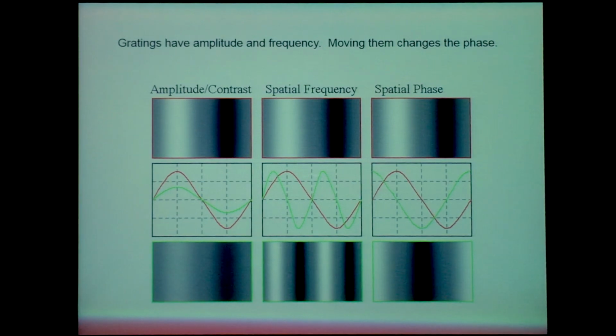And we can sort of express that in the form of a cosine curve, where the peaks represent where the atom is, and the trough represents where it's absolutely not. In the real case, we ignore this trough here. And I'll get into how we can ignore that in a minute. Now, this has a certain intensity, which is due to the atom type. So if it's a selenium atom, this is quite intense. If it's a carbon atom, it's less intense. So that's what the amplitude is, amplitude contrast.